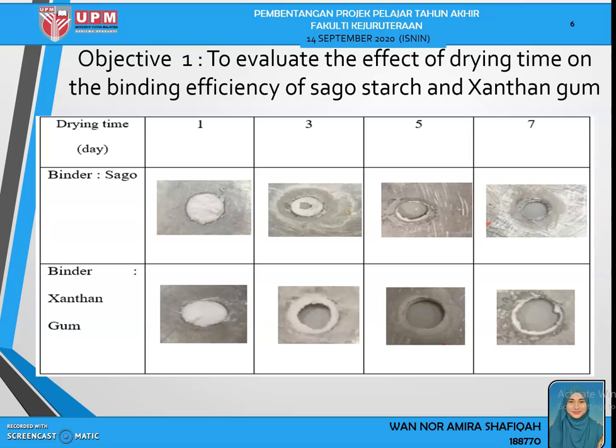So for the first objective, to evaluate the effect of drying time on the binding efficiency of sago starch and xanthan gum. Based on the image presented here, it can be observed that after day 1, the BG tablet prepared using both sago starch and xanthan gum was still wet and strongly attached to the mold. So if the sample is removed, then there is a high possibility that the tablets are cracked and crushed because the loose powder is not properly bound yet.